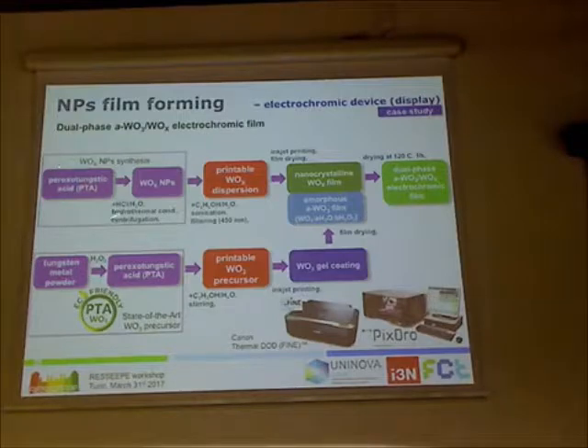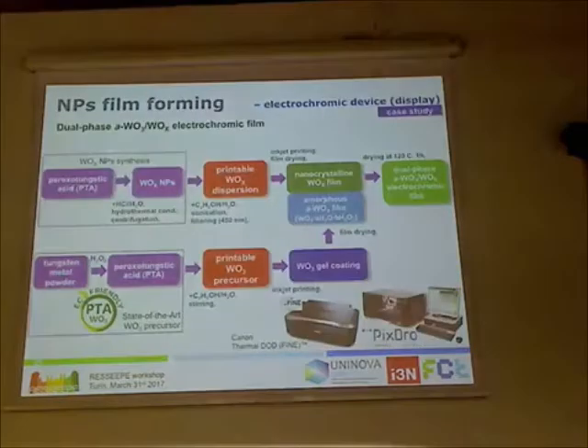We take the same kind of source we use to create the particles, and we also make a printable tungsten oxide ink. If you print this ink directly, it will result in an amorphous phase, not in particles, because here we first have to synthesize the particles and then put them in water to be sprayed. We can also use the same source to create an ink that is printable, resulting in an amorphous phase.